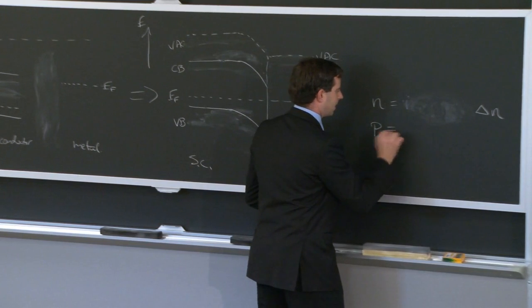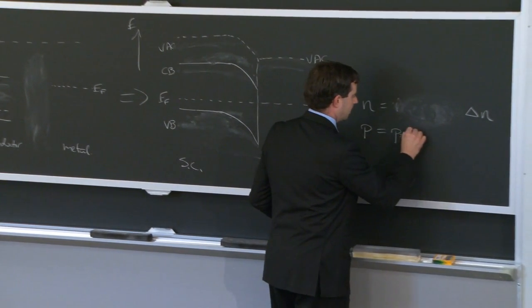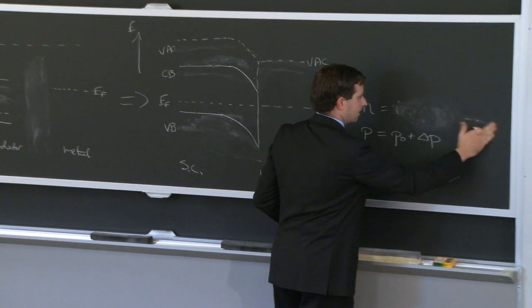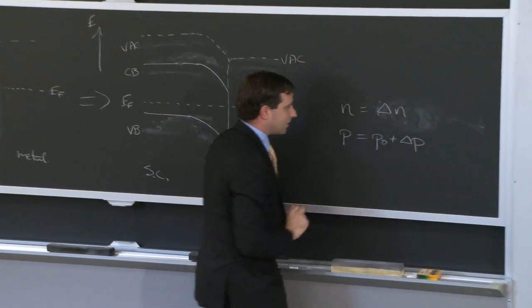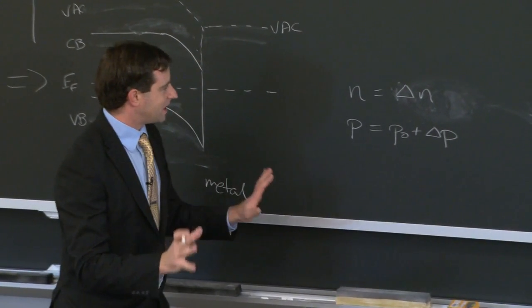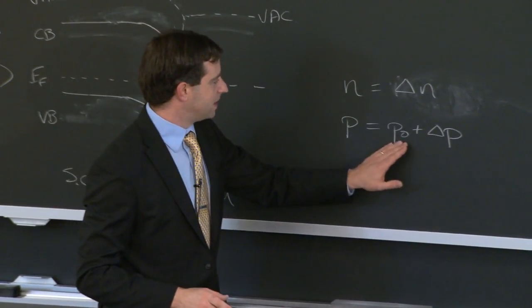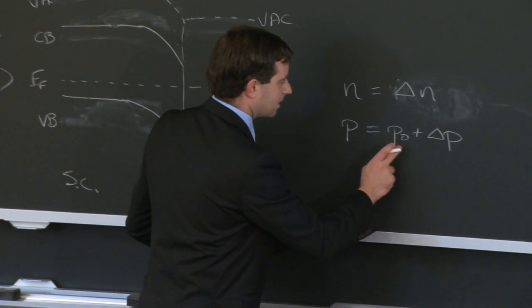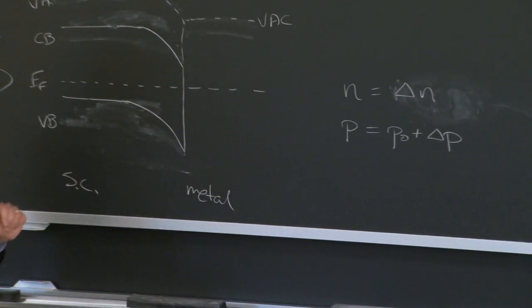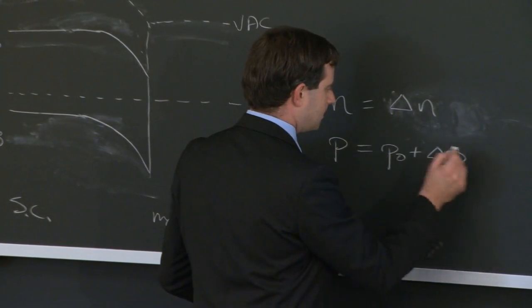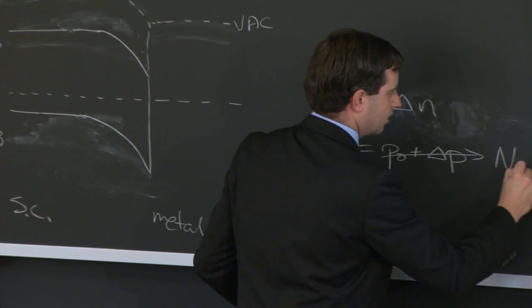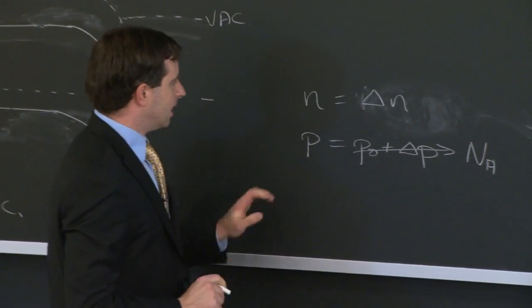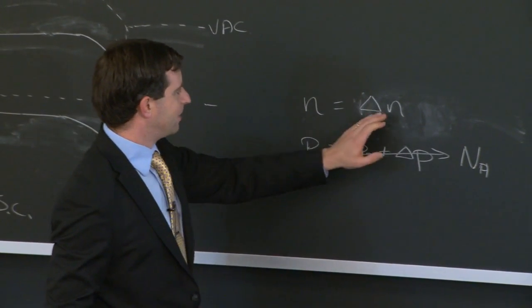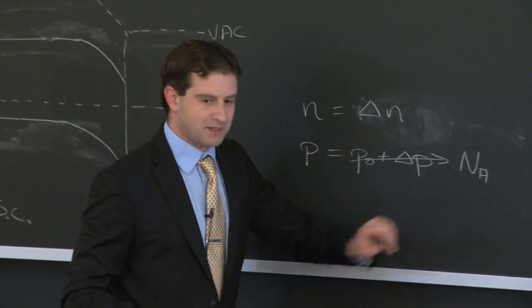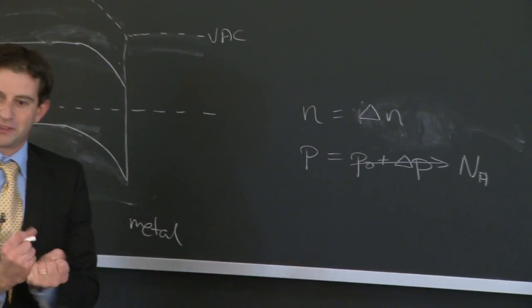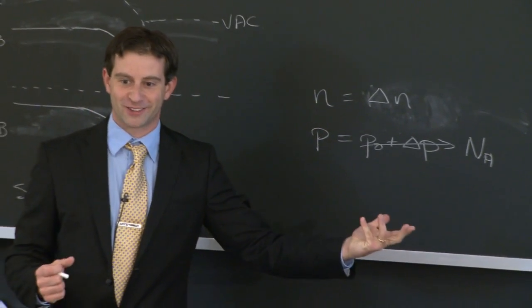Now the P, on the other hand, is going to be equal to P naught plus delta P. So let me drag this over here. The delta P is still on the same order as the delta N, let's say 10 to the 13, somewhere in that range. But my P naught is equal to the dopant density, the acceptor density, which could be on the order of 10 to the 16. So this will be somewhere in the range of 10 to the 16, driven by the acceptor concentration. And so now I have a situation in which I have 10 to the 13 electrons and maybe 10 to the 16 holes. And if I multiply the two together, I'm not getting the intrinsic carrier concentration squared